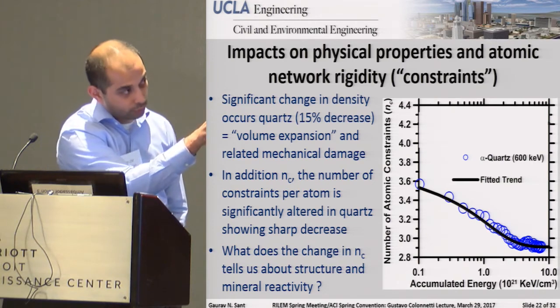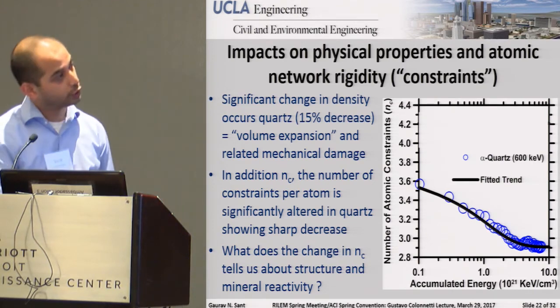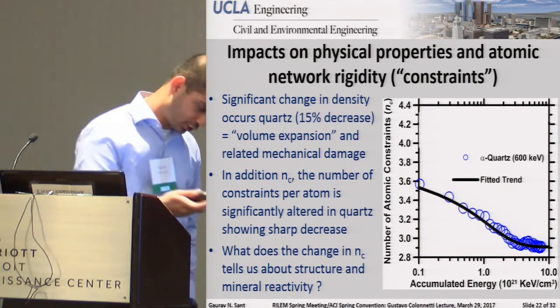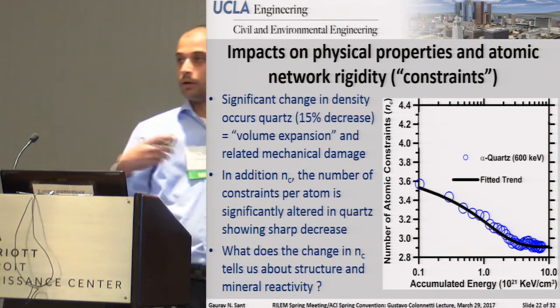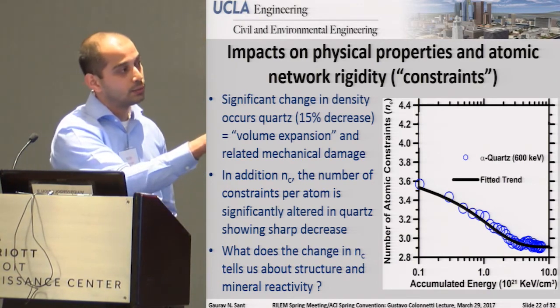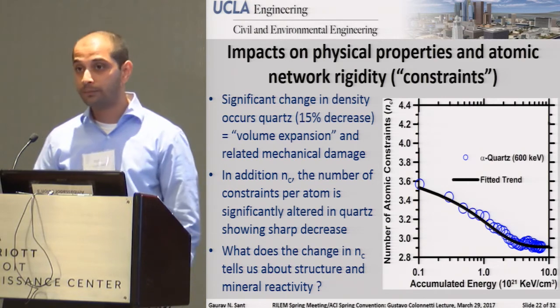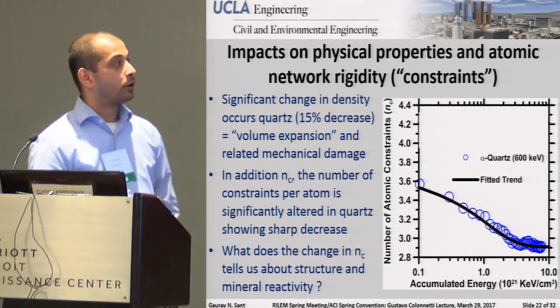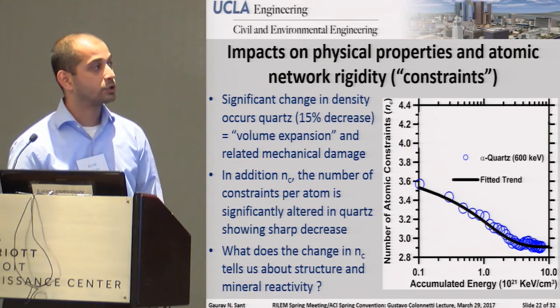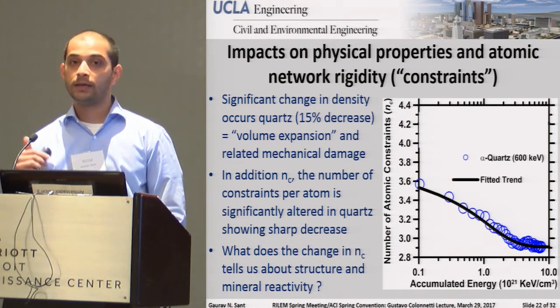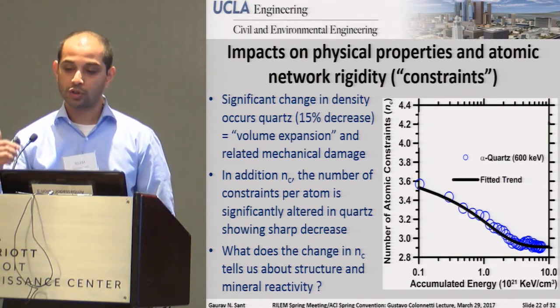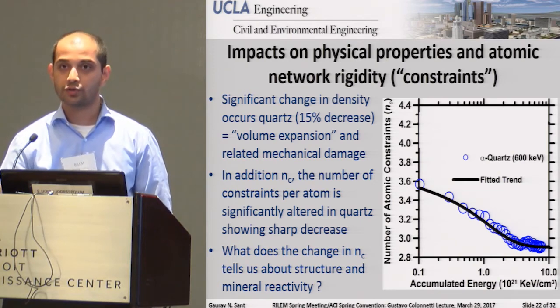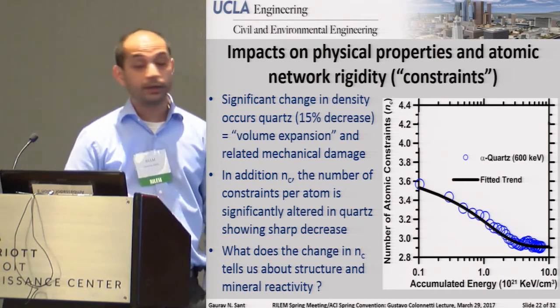As you expose it to more and more radiation, the number drops. So you go from a system that was originally stressed rigid, so you can imagine that this is a very stiff system, to a system which now eventually can be pushed over. This is quite an important thing to point out, because the first thing that you can start to tell is that as you go from a system which is ordered to disordered, so essentially structured to amorphized, you're losing rigidity.